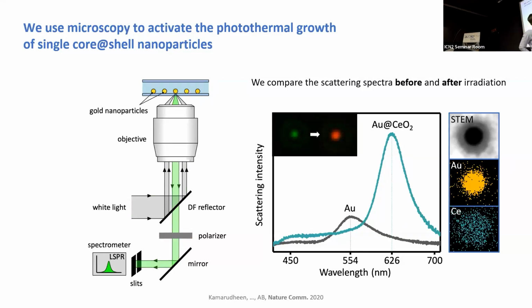You have a gold nanoparticle at the beginning that in dark field, everything is dark except that little speckle of dust that is your gold nanoparticle that scatters a lot of the green light, and so it looks green in your alignment camera. And if you measure the plasmon resonance, it will have a scattering peak at 554 nanometer that's in the green.